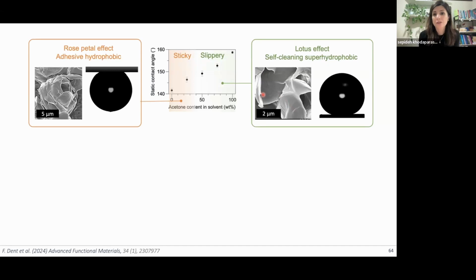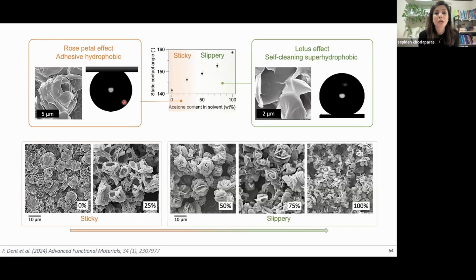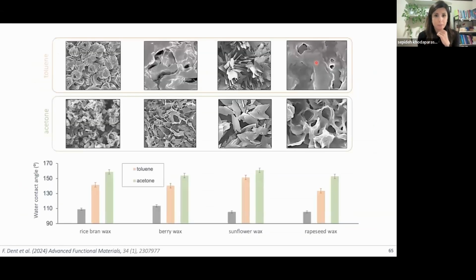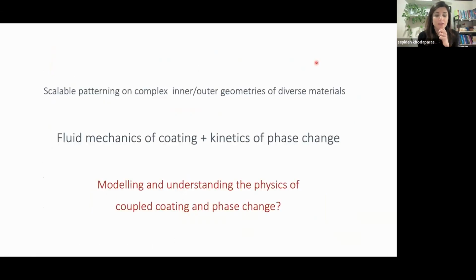So if you have smaller structures produced by fast evaporating solvents, the surface is super hydrophobic, but it's very slippery. On the other hand, if you use solvents that evaporate slowly, you get super hydrophobic surfaces, but very sticky surfaces. And you can tune these surface structures by mixing different solvents and tune the evaporation rate of the solvent and get all the different types of wetting behavior that you're after. I showed you the results for the rice bran wax, but you get similar trends when you use different types of waxes.